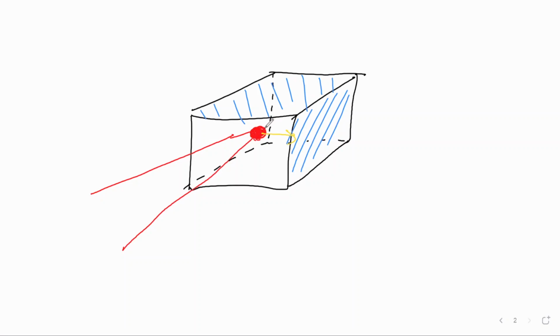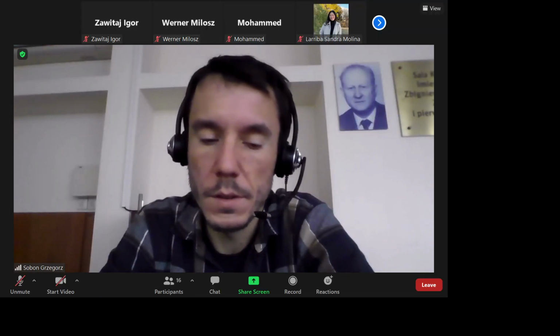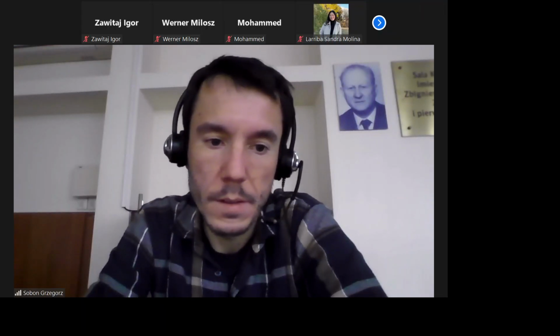So it means that we have a thermal gradient. So we induce a lot of stress into the crystal. So when we put too much power into this kind of crystal, it might get damaged, because it might either break or we can burn a hole in this crystal. So to avoid that, we are using disk lasers,